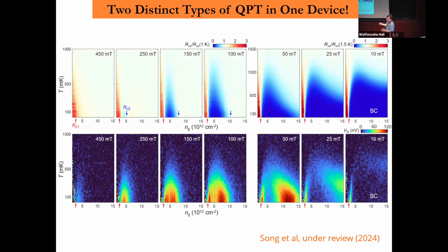So you see the fluctuation. You see the very sharp, unchanged one, that doesn't move with field, still fixed here. Very sharply, you have a sharp point where it doesn't make sense—both sides quickly disappear. It's a sharp peak. But the other phase transition, the quantum phase transition at high density, is very broad. Okay, the second one, now I'll show you, it's kind of interesting.